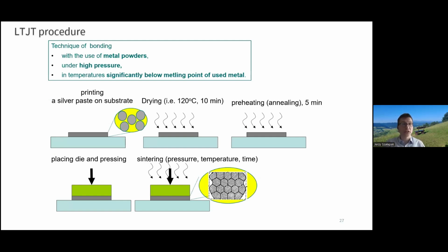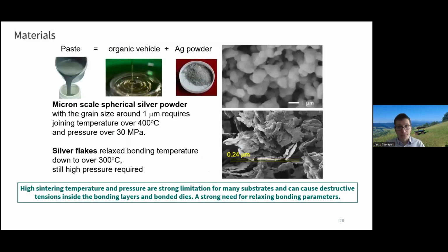The low temperature joining technique allows for sintering of metal powders at temperatures well below their melting point. To a certain extent, it is possible to lower the sintering temperature of the metal in the assembly by adding high pressure. Mounting in this technology consists of 5 steps: printing of the paste, drying, removing organic compound by annealing, arranging the mounted element, and sintering the layer with the pressure of the mounted element. The most commonly used material for sintering is silver. Of the other materials considered, gold and platinum are too expensive, and in the case of copper, assembly in a nitrogen atmosphere would be necessary. Silver sintering may be done in a normal atmosphere.